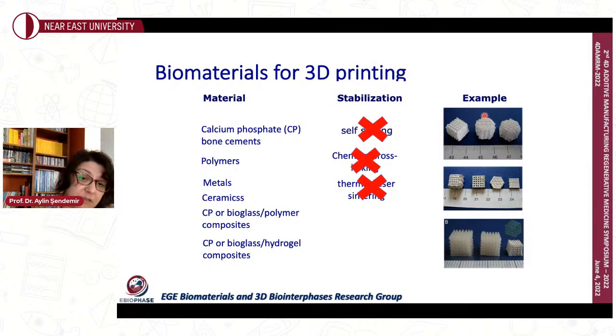There are calcium phosphate or bioglass polymer composites that are particularly applied in bone tissue engineering or dental tissue engineering. Again, they give a lot of good results in terms of tissue compatibility. But for these composites, usually thermal or chemical cross-linking is used, which again is not applicable for bioprinting, for the same reasons. So the final, and actually the only option used today, remains composites of hydrogels, where we mean polymers with high water holding capacity, highly cross-linked. Because hydrogels are very porous with a lot of water holding capacity, hydrogels can carry live cells during printing.